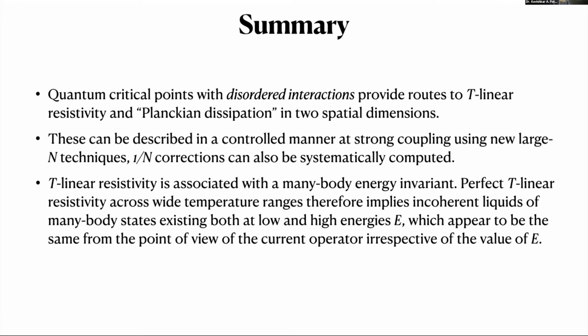What happens to your Planckian behavior when you turn on this G and have G as well as G prime? It's not Planckian anymore because the effective mass renormalization now depends both on G and G prime, whereas the transport only depends on G prime. So you get k_B T over h bar times some ratio of G prime over G plus G prime or something like that.